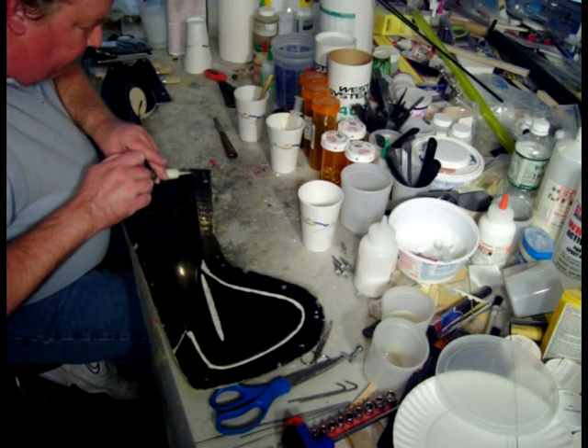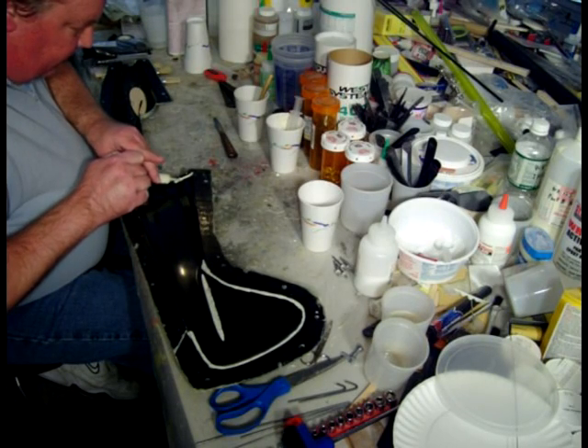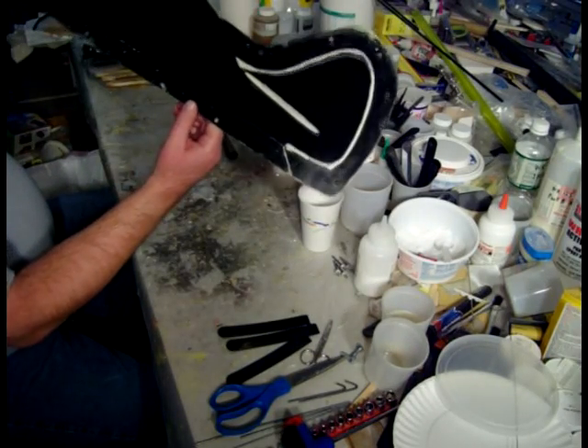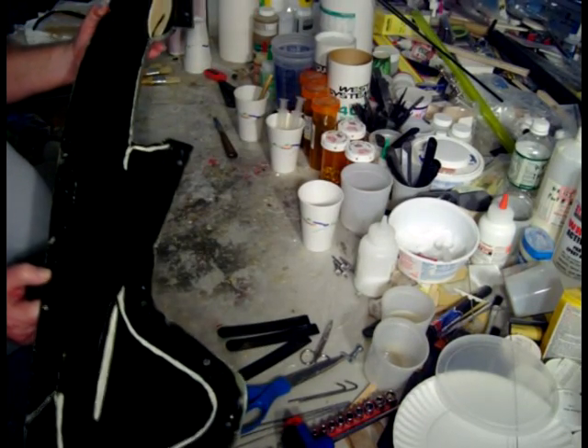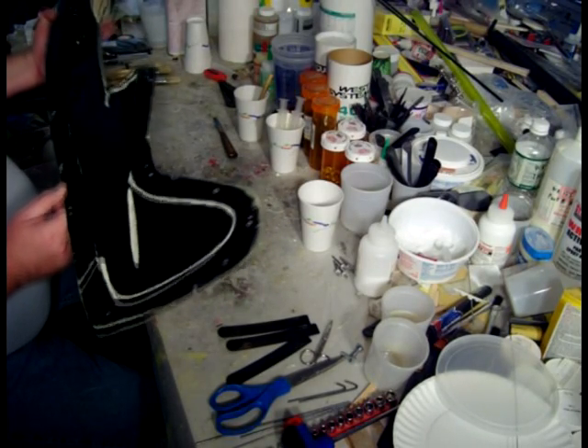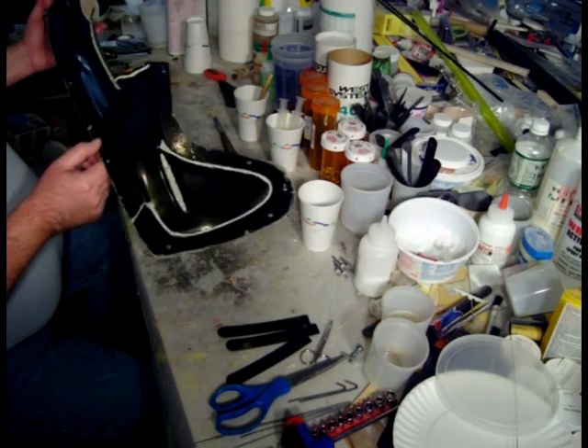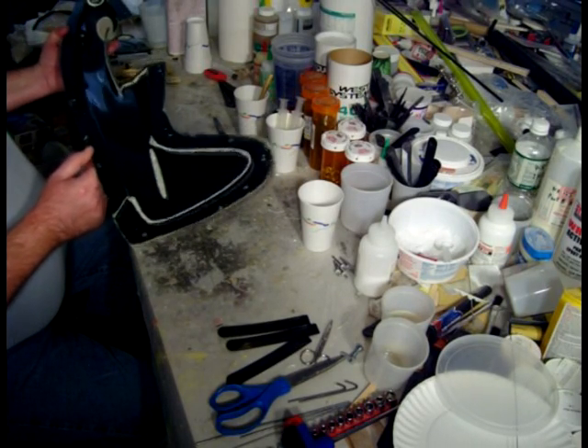And now I'm going to put the carbon fiber in the wing saddle and put the filler in the rest of the places. Now we have filler around the edges. I didn't get the filler quite thick enough — I can see it's running in the stab saddle. I needed that extra half a spoonful. Normally I use three of my little spoons of microfibers; I only used two and a half in this batch. I should have used three, but we'll be fine.